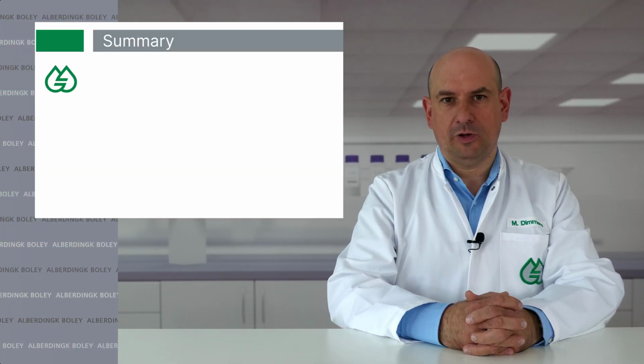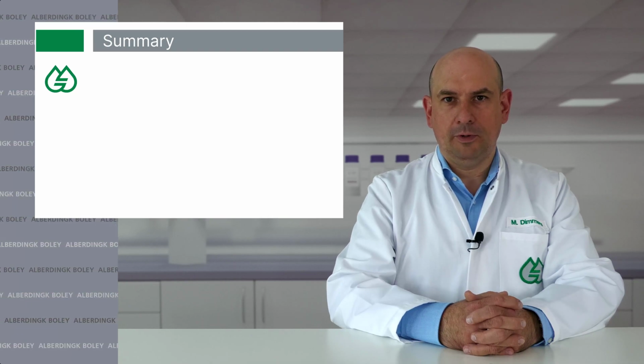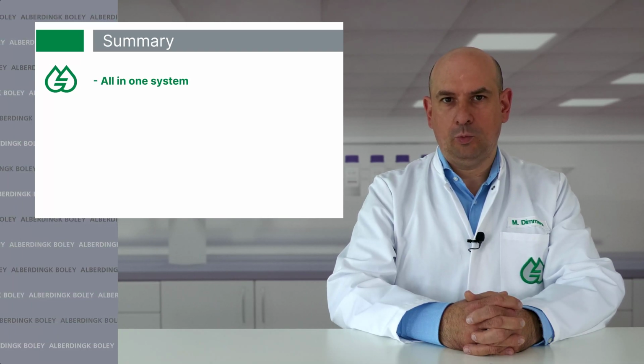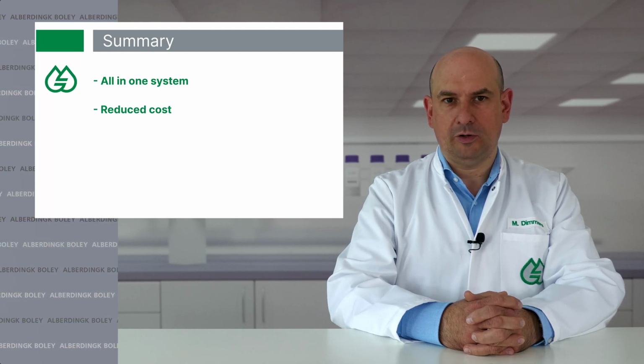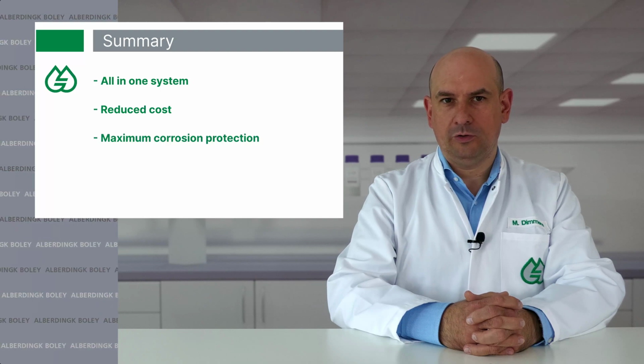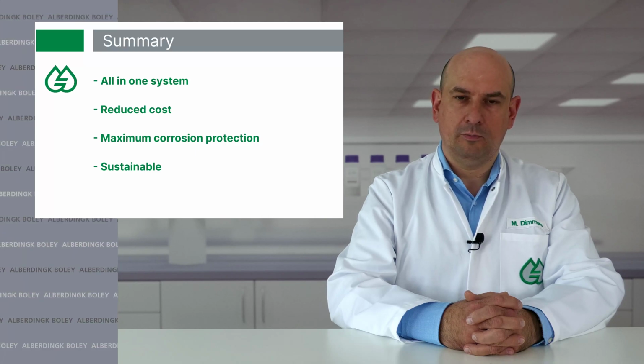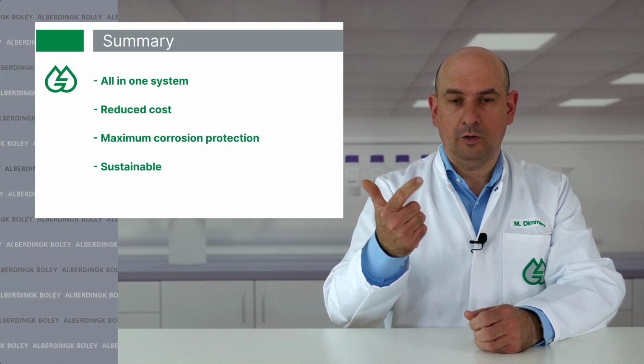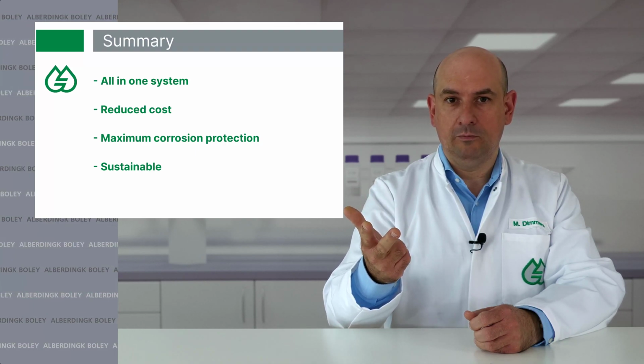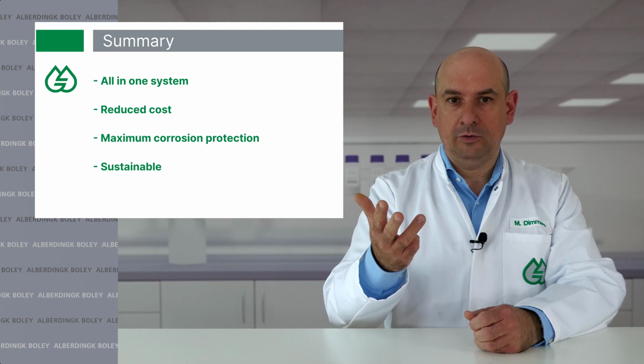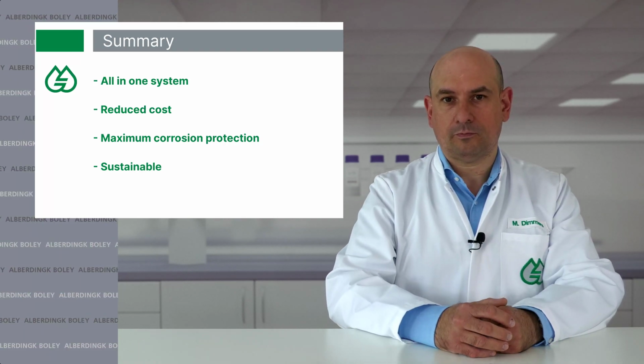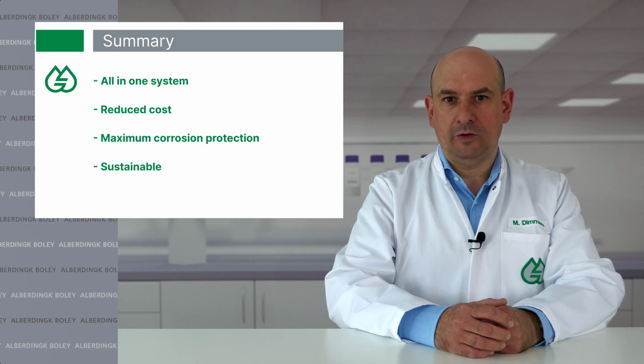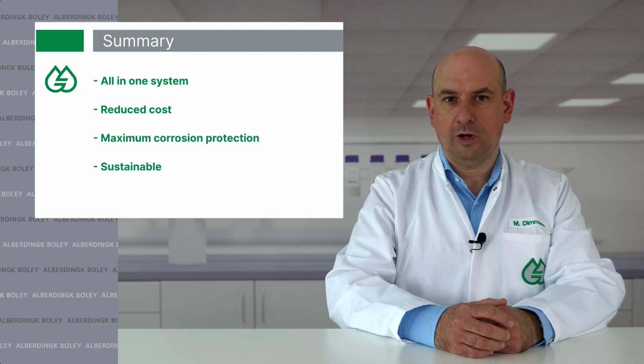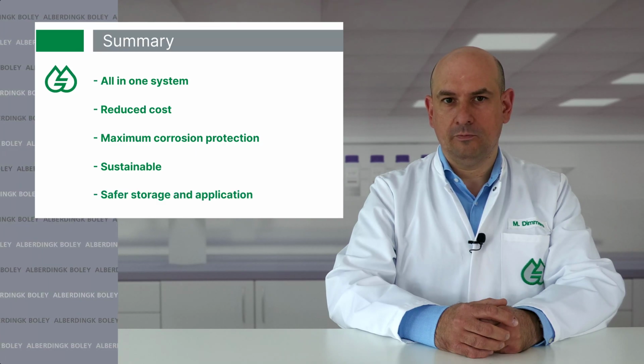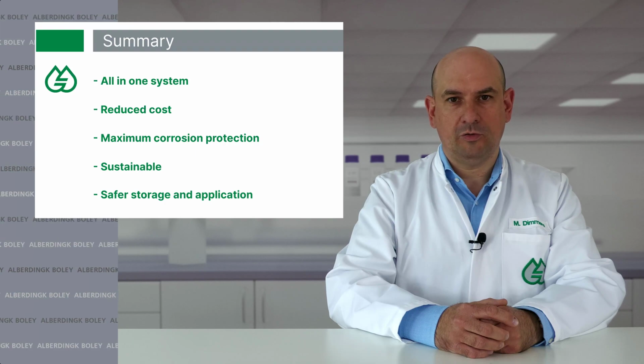Let's summarize the key benefits of AC2420. It can be used as an all-in-one system. It will reduce cost due to material and time savings. We can enjoy a higher security due to a maximum of corrosion protection, and you will have a more sustainable product, meaning it's water-based, it's zinc-free, it will be very low VOC, very long-lasting, and using a reduced number of coats. On top of that, you will benefit from less weight and cost due to the lower dry film thickness required to achieve the corrosion resistance. And because it's water-based, it's much safer to store and to apply.